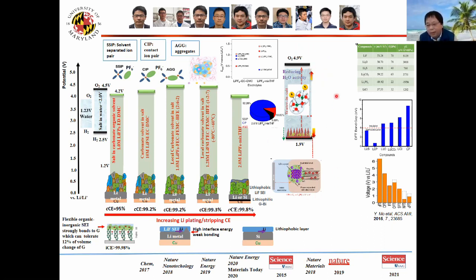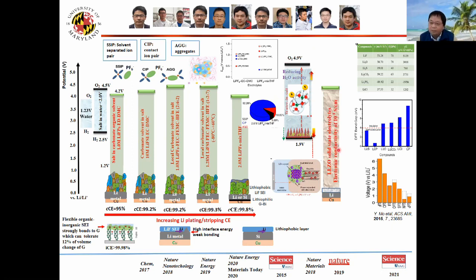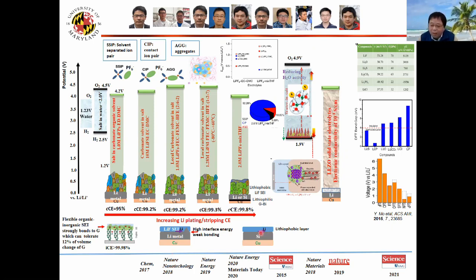This looks like there are still a lot of new things we can develop. And then, solid-state. The whole idea is we do not want the solvent to reduce — we want the ion to reduce — because we want inorganic SEI. But solid-state inorganic would be perfect and should be much better than liquid. But we still have a problem right now: based on this theory, solid-state should work. We say lithium fluoride is the best SEI component, but in solid-state up to now we do not have any fluorinated solid electrolyte. All solid electrolytes are oxide and sulfide, and we already know sulfide is bad.